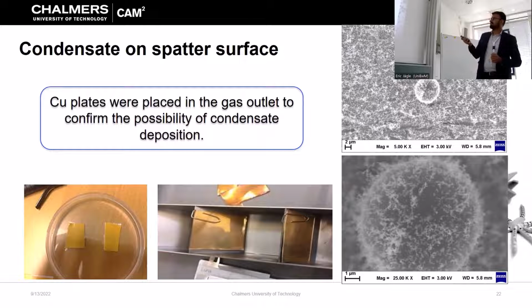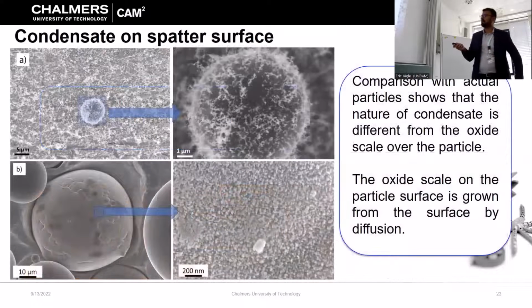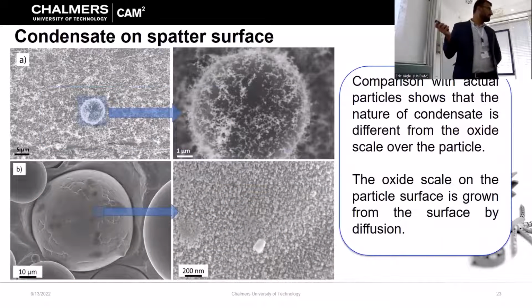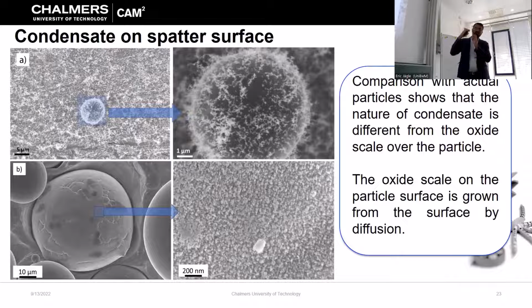And what we found on that copper plate is a very fibrous condensate deposited on the surface. But if we compare it with the spatter, it is quite different. It is not the same. Also, if you go back to the gas outlet and imagine, spatter coming later on will deposit on top of it, and it will not have enough chance to get too much condensate. So there might be a little bit of condensate during that process, but it is not as much.